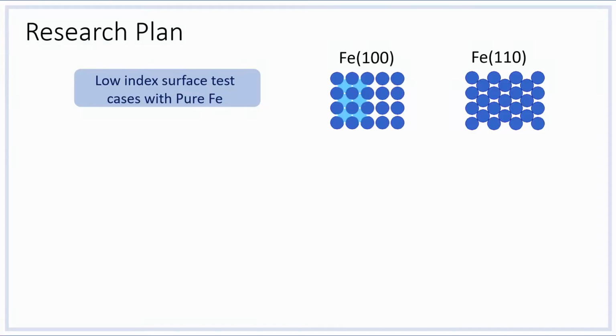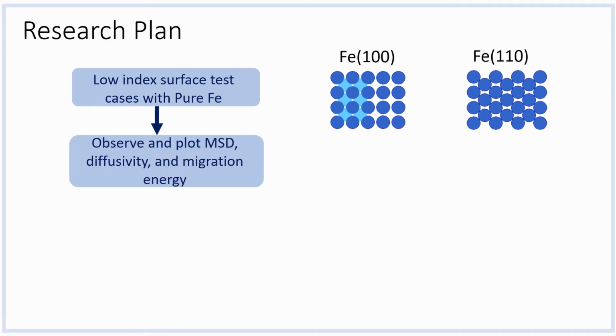At the beginning of the summer, I developed a research plan for how I would progress through this project. I would start by creating test cases of pure iron structures, focusing on the 100 and 110 surfaces. If you're not familiar with that, that's just how the atoms are packed into the surface structure. And then I would add an extra atom and observe how that atom would diffuse across the surface over time, plotting the mean square displacement, and from there being able to get the diffusivity and the migration energy.